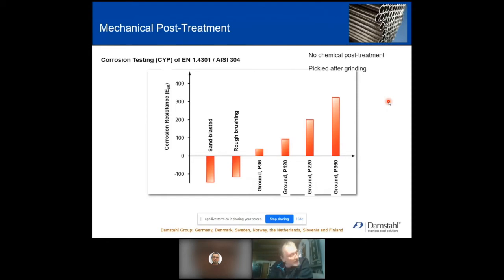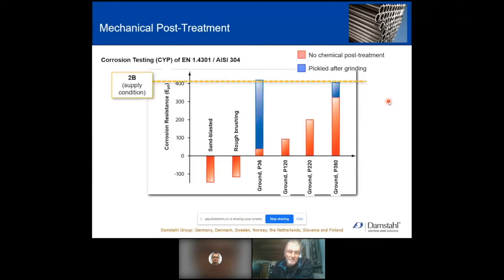But then some people may say, okay, what if we applied a chemical surface treatment? Then we get results like this. And we should remember that the 2B sheets, which almost every single pharmaceutical or dairy tank is made of, are actually pickled from the mill. So why do we polish a tank to grit 220 when actually the steel we bought at the mill is up here? That's not good business, but sometimes there are too many architects.